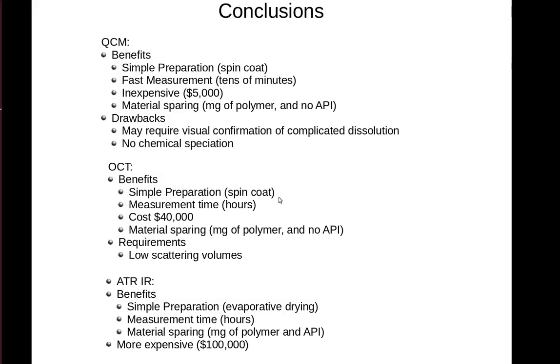Again, the sample preparation is fairly simple, spin coating on a microscope slide. The measurement time is a little bit longer, hours, because the film is a bit thicker than we'd use for a QCM based on just the resolution that we can get with the OCT. The cost is a bit more. It's about $40,000. It's also very material sparing. It does not use API if we don't want to.